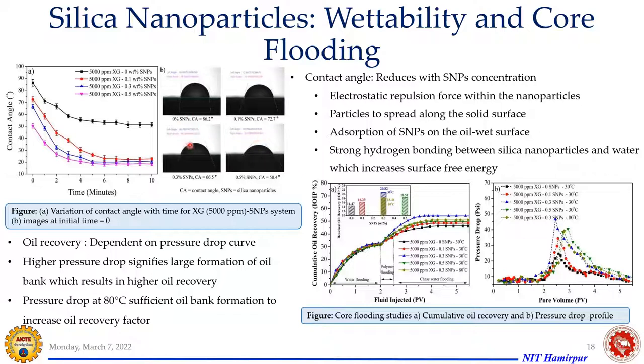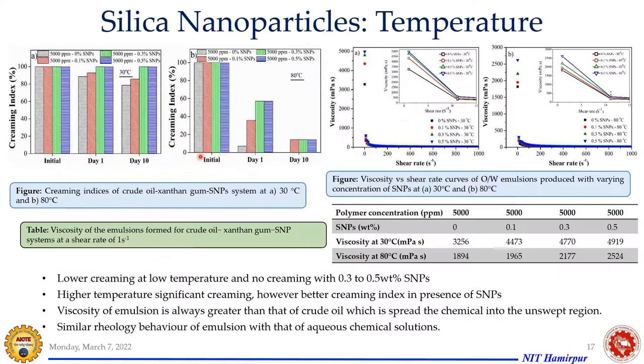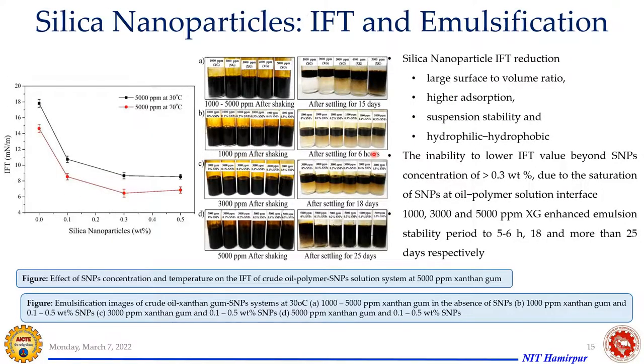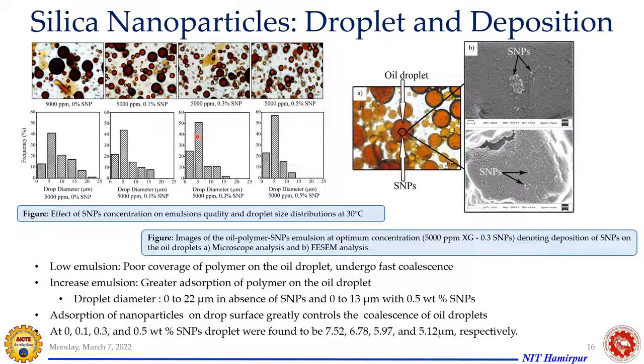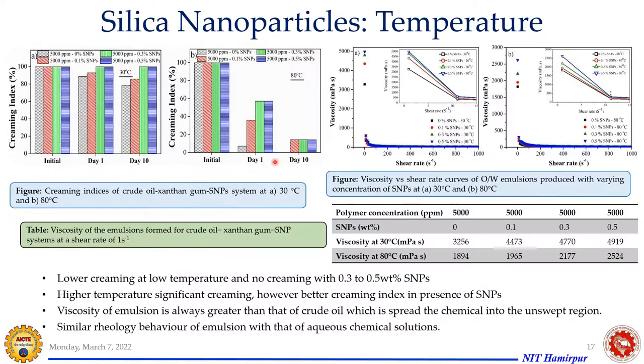So you can see now the oil will be away from the surface, and once we use chase water or any other means of flooding, it will be taken out to the surface easily. As you see here, we have studied the IFT data and emulsion properties in detail, with the droplet size distribution, the emulsion patterns, the creaming index, and the rheological properties. So whatever mechanisms were responsible, we have already studied. Now the question is, how should we predict? Based on this data, we could predict that 0.3 would be more or less the optimum, 0.3 or greater than that.